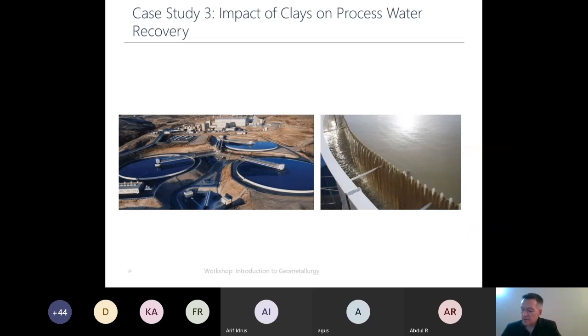Thickeners. The thickeners, these facilities. Thickener is critical to allow recovering of at least 30% of the process water prior to sending this tail slurry to the final deposition. The capacity of thickener might be strongly affected by clay content, reducing sedimentation rate and consequently water recovery.